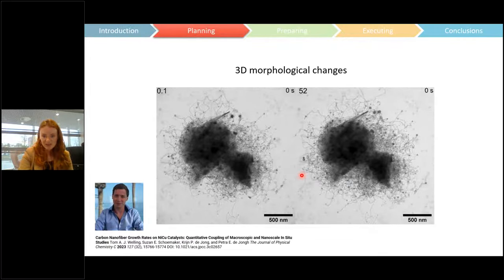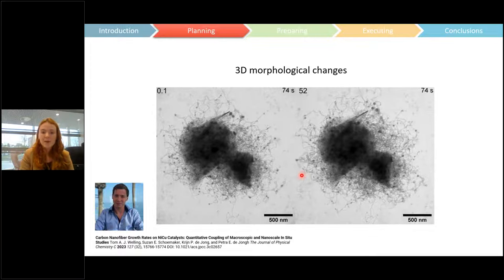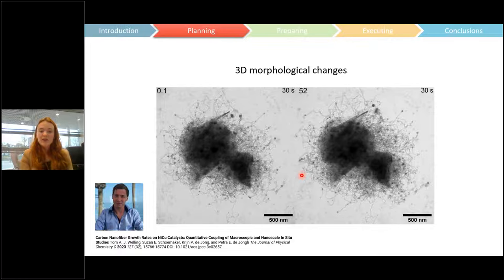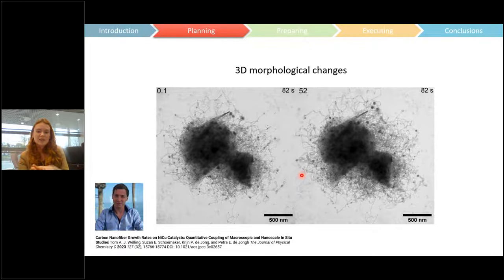And then for the 3D changes, which can be quite challenging, again, I brought up this experiment from Tom Welling. It's published. You can check him out online, the reference is there. But he studied carbon nanofiber growth. And one thing we didn't quite consider before we studied carbon nanofiber growth was the fact that the carbon nanofibers also grow in the Z direction. They also grow in 3D and they grow up and you lose focus on them, and it's very difficult to track that. It's also very difficult to track ones that haven't grown, you know, that seem to be growing flat. Are they growing flat? It's very hard to tell.